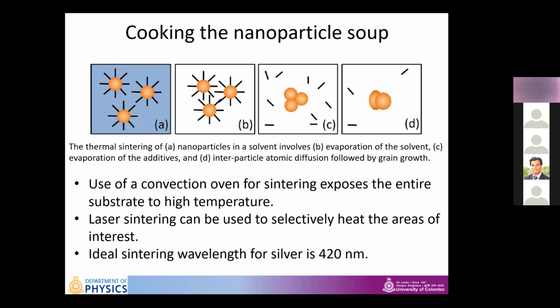You can cook the nanoparticle soup with a laser. A laser with matching frequency though. Since at a matching frequency, almost all the energy is absorbed by the nanoparticles, we can assure minimal heat damage to the substrate.